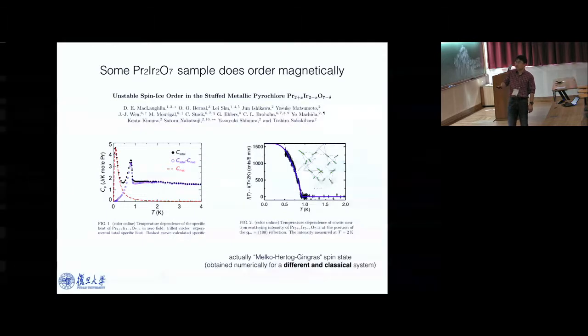So neutron and specific heat measurements see a lambda peak transition at 1 Kelvin, and neutron diffraction sees this particular magnetic order in the spin ice manifold. This is spin ice order. The system orders in a 2-in-2-out manifold, but this particular 2-in-2-out manifold breaks translational symmetry. So the magnetic cell is twice larger than the crystal unit cell. So this is the neutron measurement.